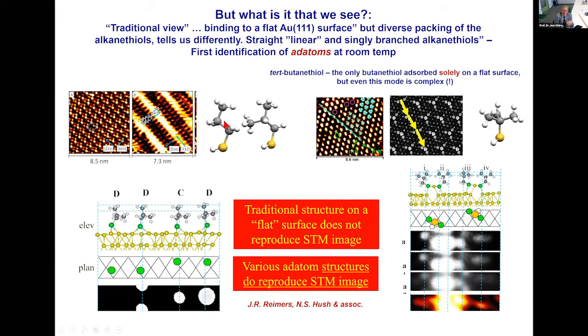If you look at these straight alkane thiols, for example, these two, either the straight or the singly branched alkane thiol, then it turns out, if together with our partners, Jeffrey Reimers and Noel Hush and their people, they calculate the traditional structure, the alkane thiols directly on the flat surface, then the electrochemical scanning tunneling microscopy images cannot be reproduced. Reproduction requires a different mechanism. What happens is, there's also experimental evidence for that in the form of pits and vacancies and so on. A gold atom is dug out of the surface.